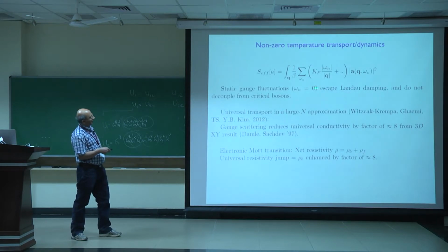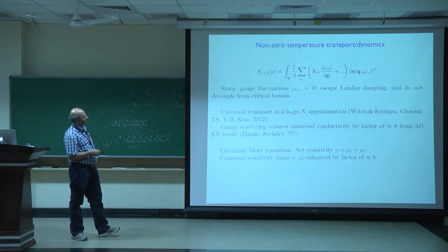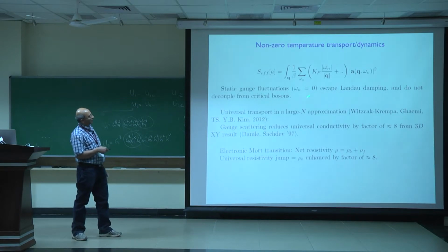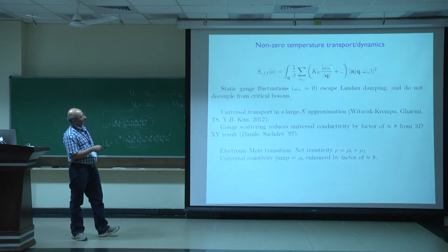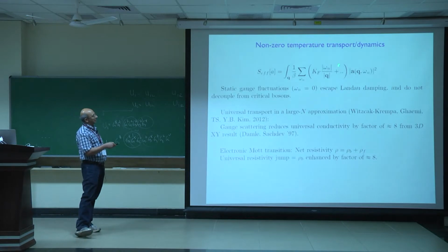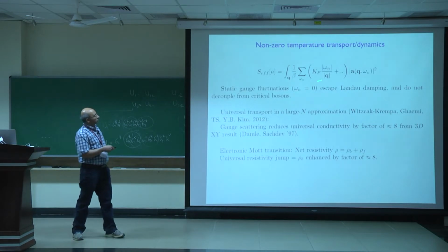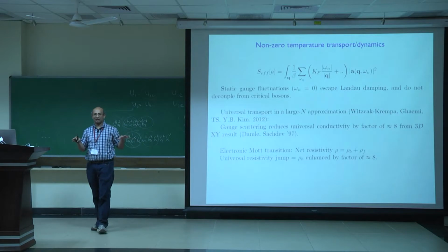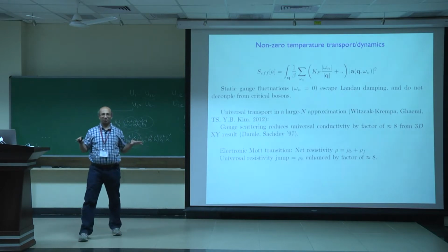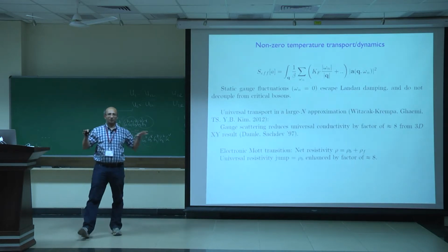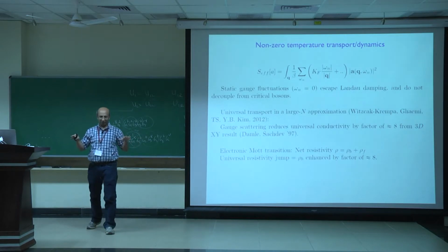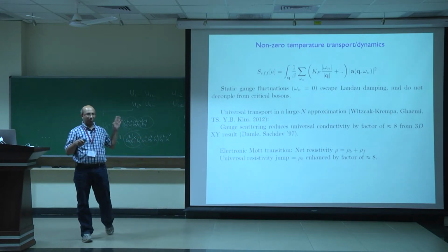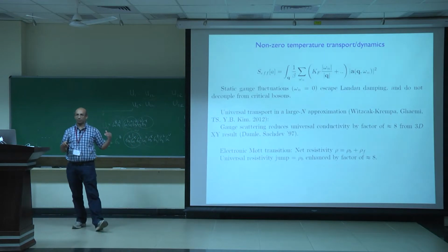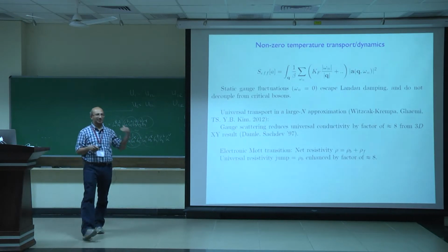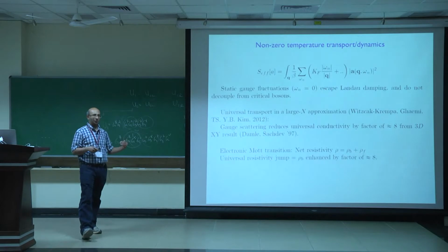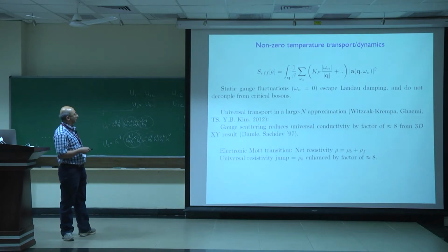There's a zero Matsubara frequency fluctuation, which are the static gauge fluctuations, which are not Landau-damped. Right? The Landau damping is not effective at zero Matsubara frequency. So those static gauge fluctuations survive at non-zero temperature, and they do not decouple from the critical bosons. So the gauge fluctuations decouple from the critical bosons because of Landau damping, but at non-zero temperature, there are static gauge fluctuations that don't decouple, that are not Landau damped, and we have to take them into account.